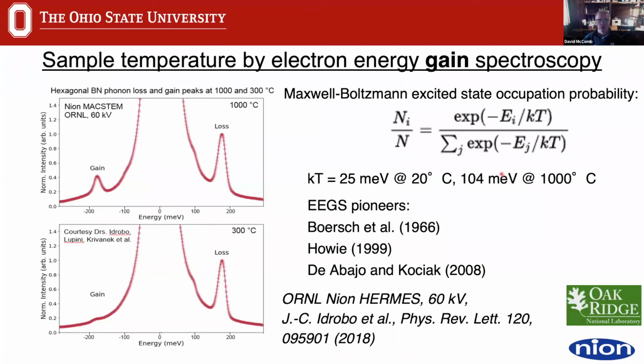So what does that enable? Why is that exciting? I've indicated that we can get to really low energy parts of the spectrum, and now we're pushing this such that we're plotting our energy loss in millielectron volts. Here's a very nice example from the group at Oak Ridge, led by Juan Carlos Idrobo, showing how you can do something that's actually incredibly difficult in the electron microscope, which is to measure sample temperature. And they found a mechanism to do this by doing electron energy gain spectroscopy.